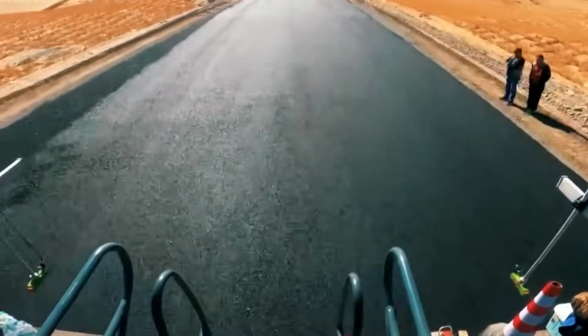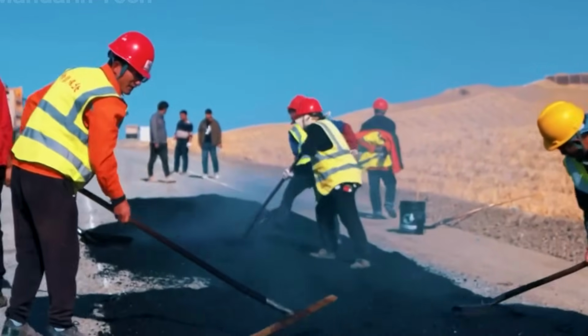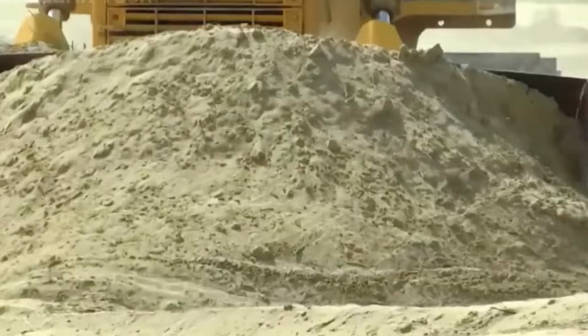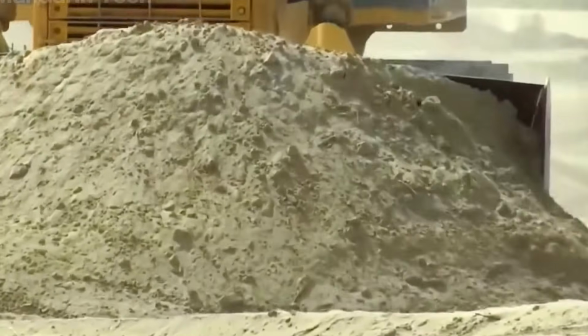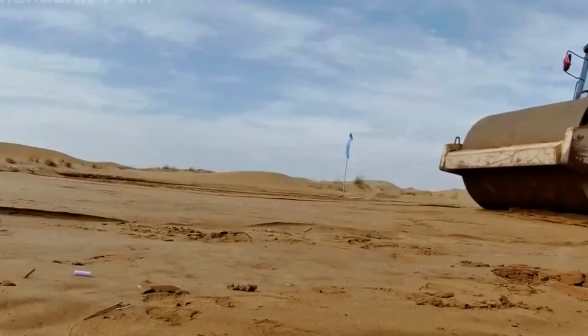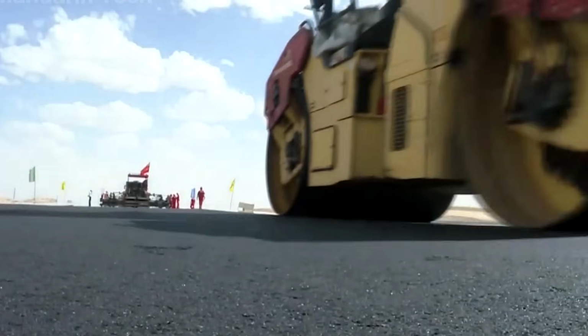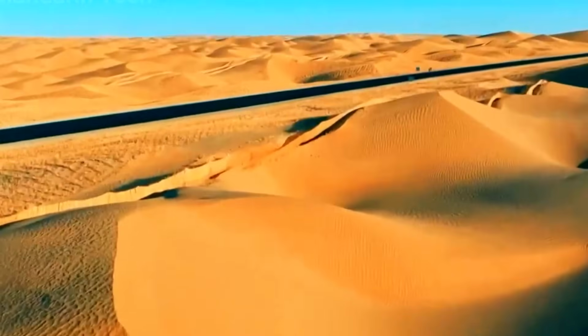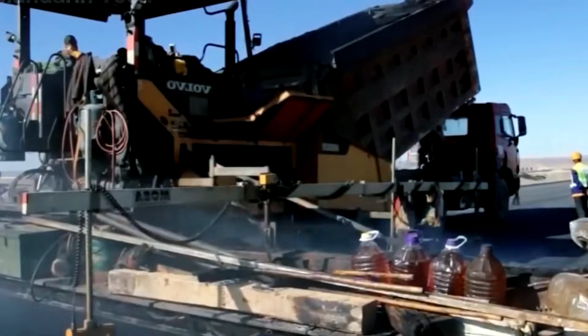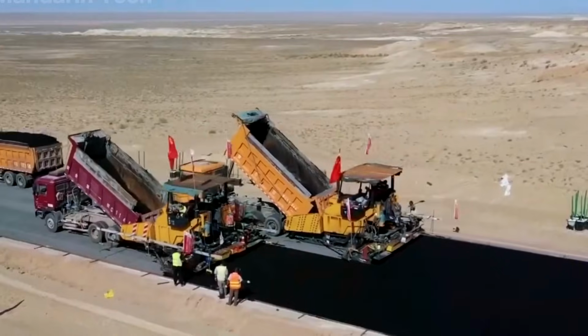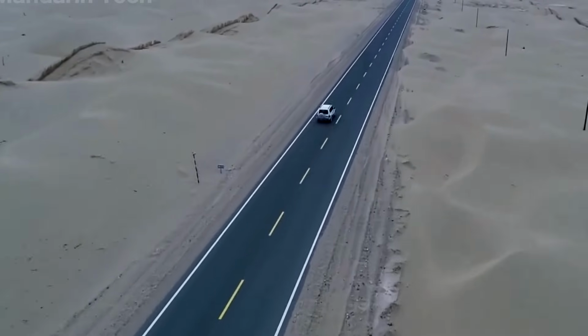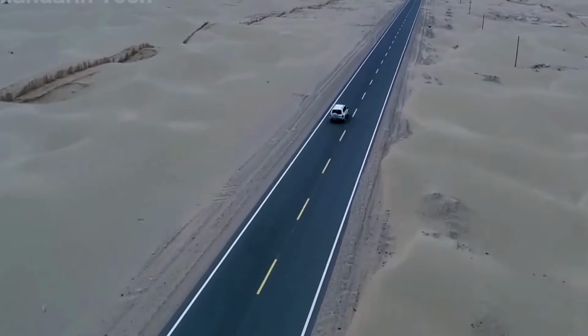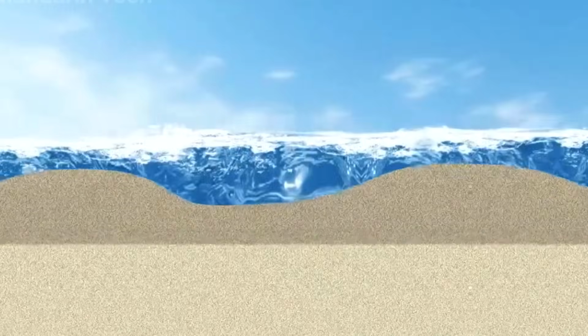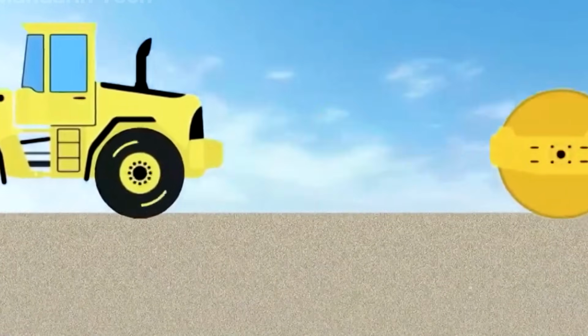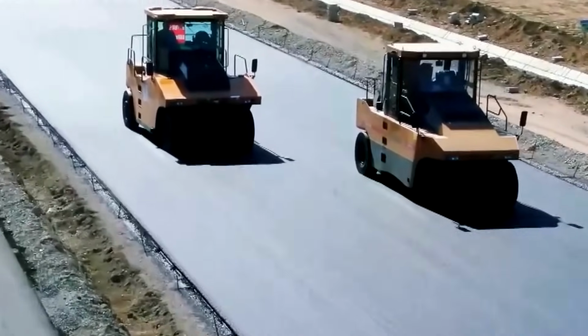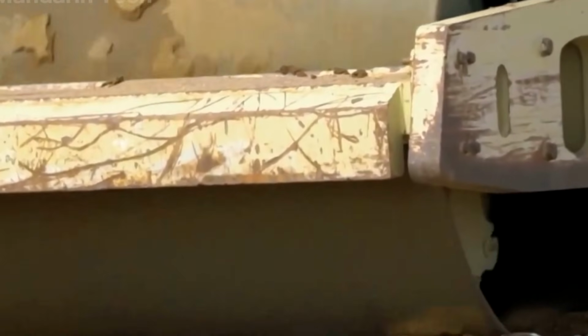Consequently, supervisors verify flatness with laser beams, allowing no more than 3 millimeters of deviation per meter. As the desert wind cools the surface, the asphalt hardens into a flawless black sheet, tough enough for extreme climates. Workers spray a protective seal coat, giving the road a deep shine and locking out moisture. After 4 grueling years, the 4-lane highway connects the far ends of Xinjiang, showcasing an achievement that impressed even American engineers.